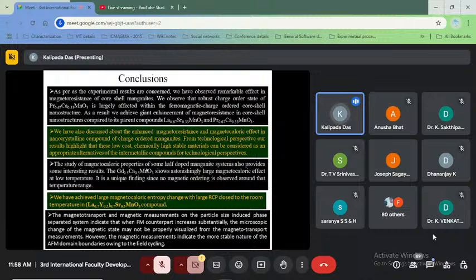And also I have shown some large values of the magnetocaloric effect in the case of the gadolinium calcium manganite and dysprosium calcium manganite series. And also for room temperature application, yttrium doped lanthanum strontium manganite exhibits larger RCP and magnetocaloric entropy change, as well as the training effect, indicating that the metastable state of the nanocomposite form gets enhanced with respect to magnetic field cycling and becomes a stable magnetic configuration.